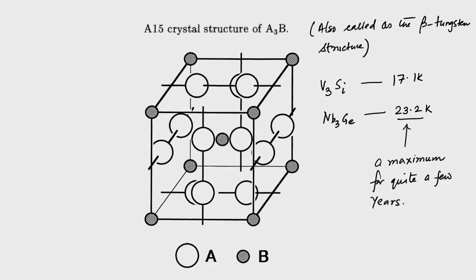And it is proposed that with the electron-phonon interaction, this is the maximum Tc that one can have. As you understand, this temperature is very low, nearly 250 degrees below the freezing point, and that is the freezing point of water, of course. So for industrial applications, or any applications related to making superconducting wires, etc., this temperature is not a suitable one. The numbers that we show here are certainly not viable to achieve.